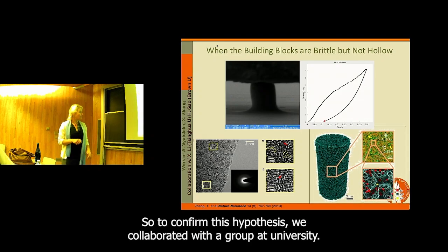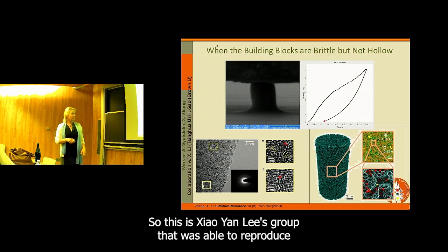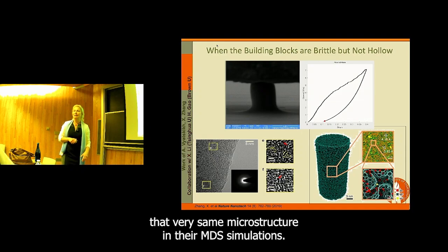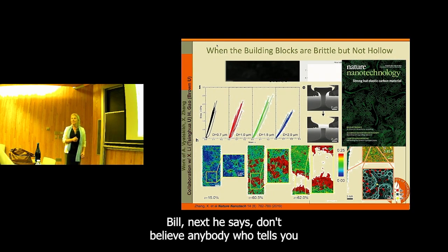To confirm this hypothesis, we collaborated with a group at Tsinghua University. This is Xiaoyan Li's group, which was able to reproduce that very same microstructure in their MD simulations. And then, of course, my former advisor, Bill Nix, always presents this challenge to me. He says, don't believe anybody who tells you about ductility in compression. You can make anything ductile in compression.